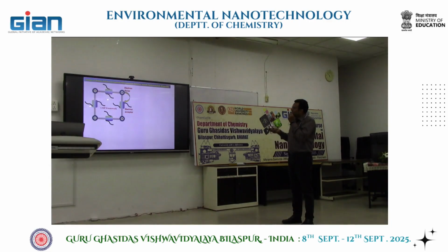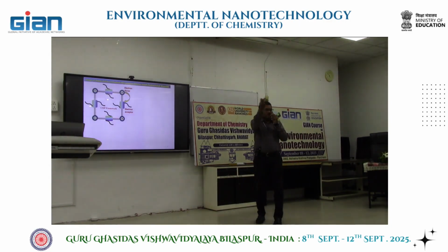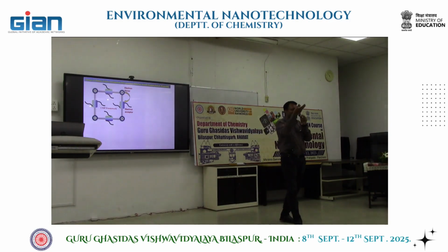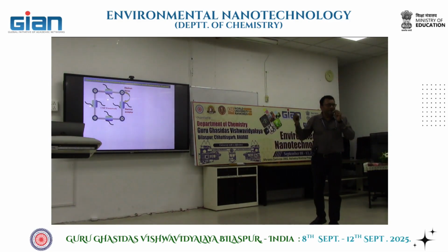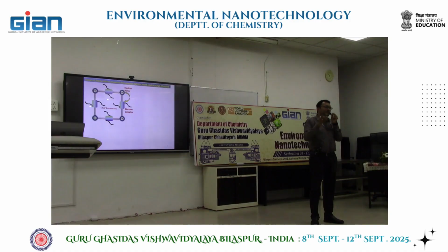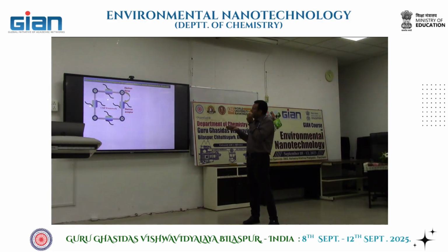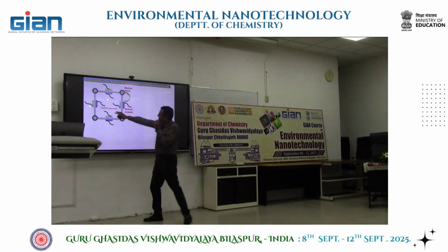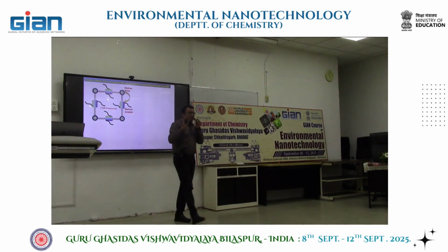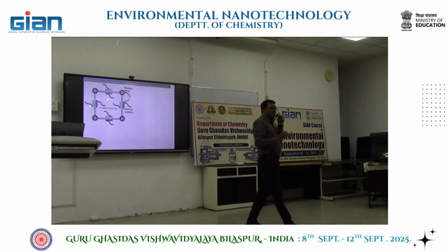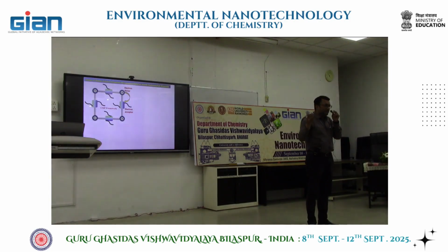The second thing is the conjugated. You are all chemists, even physicists, so you know better that it has a continuous conjugation, and only then can it help to flow the electron from one end to the other. Then the microporous. Here you can consider this like a pore, okay? Which basically helps again to provide the high surface area, to facilitate the substrate diffusion inside the pores.